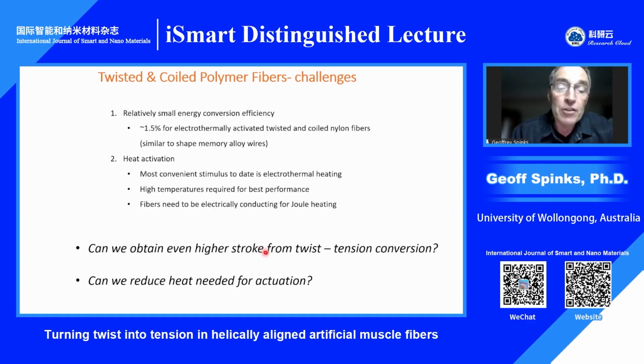Now, they're not without their challenges. And I'd like to now move on to talk about how we've addressed these challenges. First of all, quite low energy conversion efficiency when we're talking about the thermally actuated twisted and coiled fibers. It might at best be about 1.5% of the heat energy is converted into mechanical energy. And that's about the same as what you get from shape memory alloy wires, but it's obviously very low. So we'd like to increase the energy conversion efficiency by at least an order of magnitude.